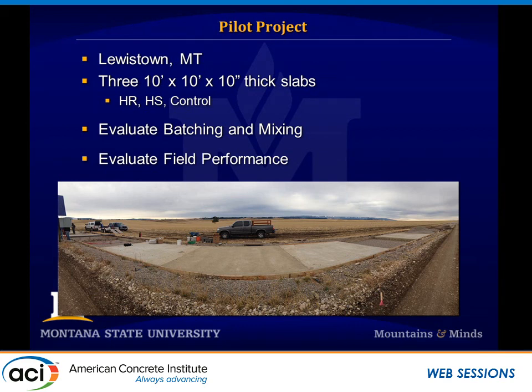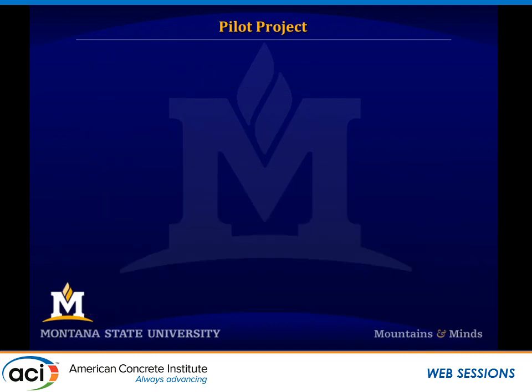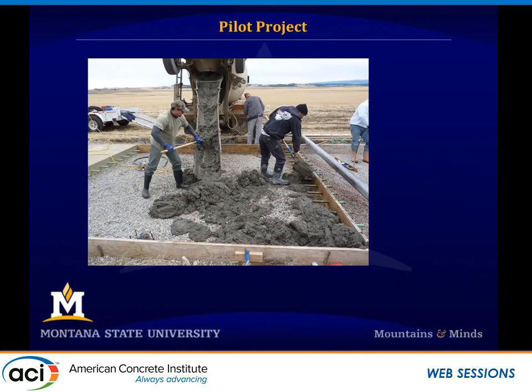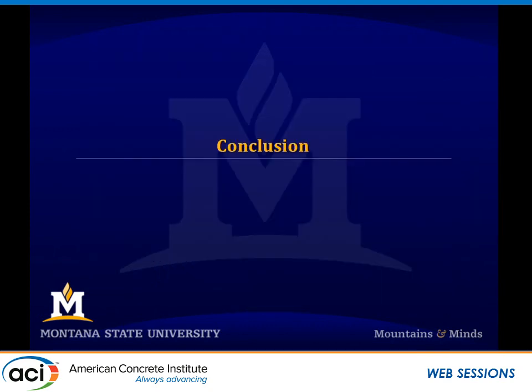I have to boast on my strength values and the predictions. On one of these test slabs in our high RAP mix, at 28 days, the concrete strength was 3,001 psi. I mean, it looks fabricated, but it was real. And that was the average of 3 test cylinders. It was pretty interesting. So then we applied it there. Here's some pictures. We slump adjusted it, and we're evaluating the field performance. They've been down for about a year, and we're just monitoring to see if there's any curling associated with it, or how it's handling the traffic and stuff. Here are some pictures of them constructing those slabs.